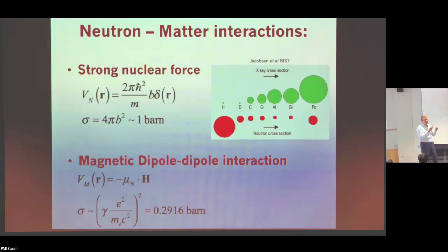However, there's a dipole-dipole interaction, because the neutron has a dipole moment 1,000 times less than the electron's dipole moment, but that gives us sensitivity to the spatially varying internal magnetic field in the material and allows us to couple to the electron, even though we have no charge. Through the dipole-dipole interaction, we do actually couple to the spin of the electron. So we know exactly what the interactions look like.